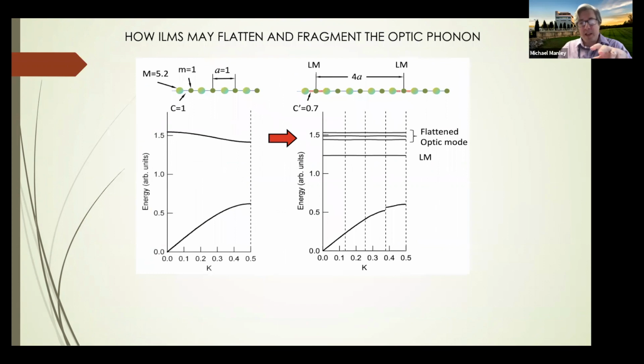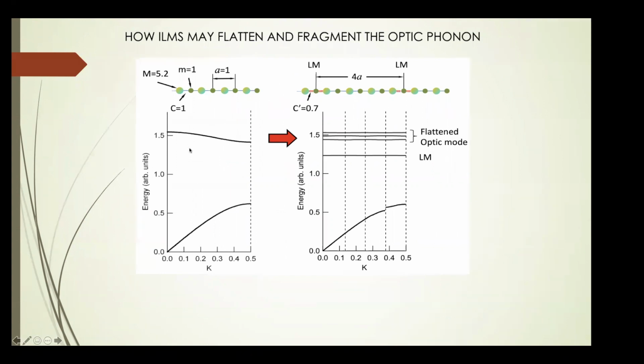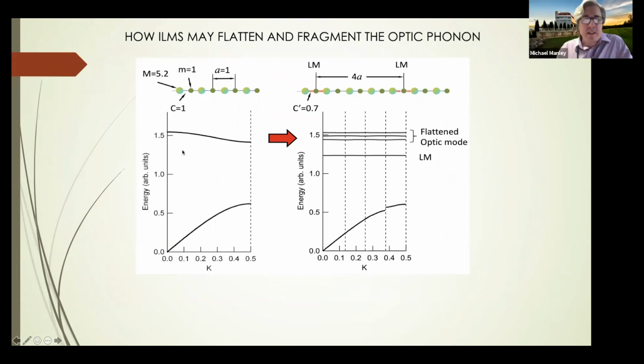So I want to explain something that it actually does pick up, but it's tricky to understand why it happens. Why does the whole branch go flat when you get this localization? I'd actually seen this before, so I had an explanation in the back of my head. Take a simple model, like the problem for phonons in Kittel: you have a one-dimensional lattice of atoms, and if you make two atoms, you get an optic phonon. The optic phonon is like your asymmetric mode, where everything moves out of phase. The acoustic phonon is like your symmetric mode, where everything moves in phase. You get this optic mode.